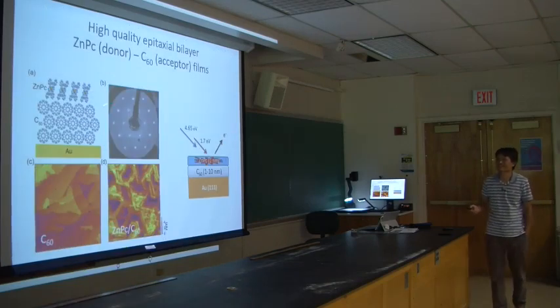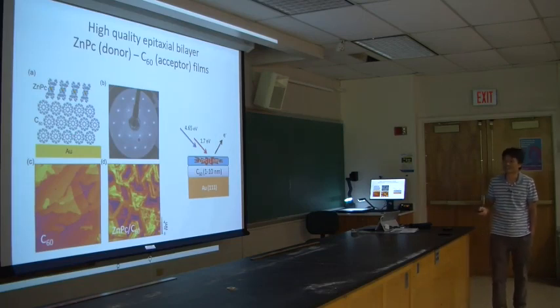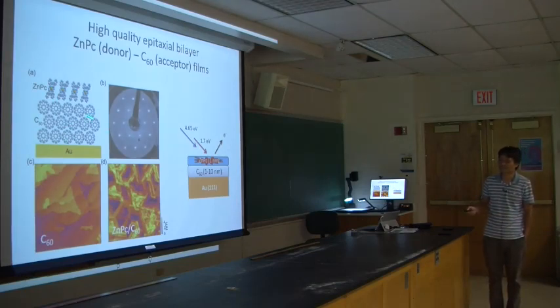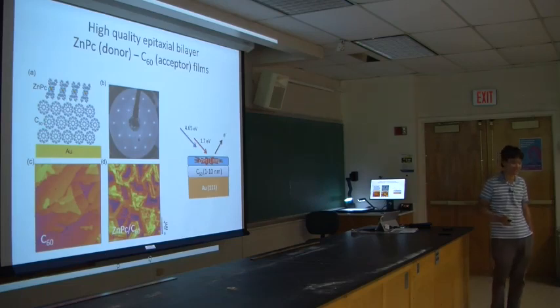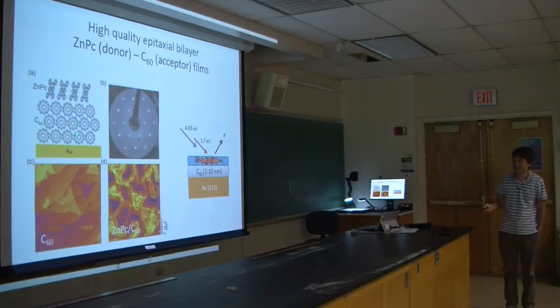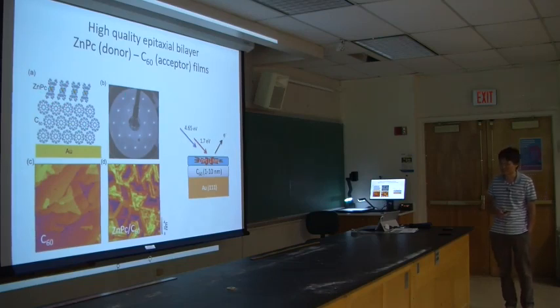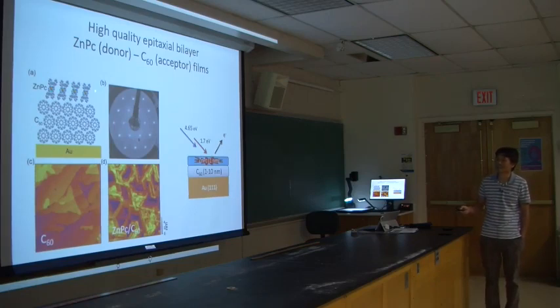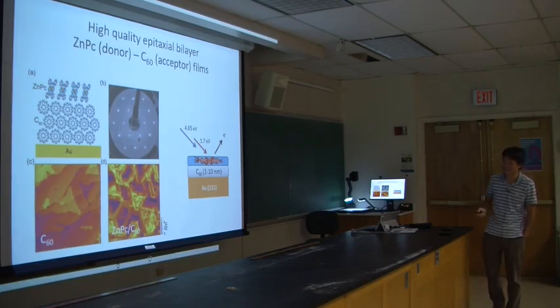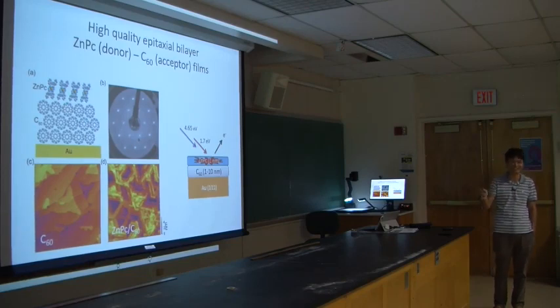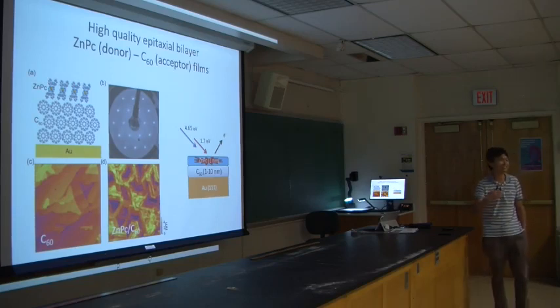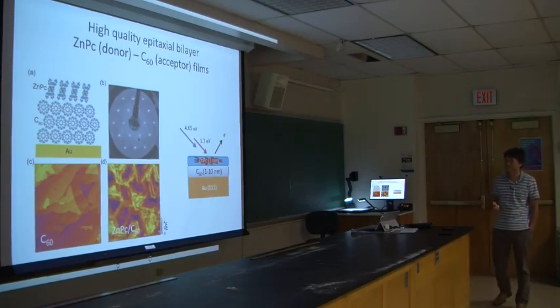So what we did is use a donor-acceptor interface, and we usually try to grow really well-controlled samples. In that particular experiment, we grew C60 molecules onto a single crystal gold surface. We have really nice epitaxial C60 on gold, and you can see that from the diffraction pattern here. Then we put the other molecules there. It turns out that in that case, these ZnPc molecules stand up and form a stack on top of the C60 molecules. We did some sample characterization, so we know the molecules are oriented the way that we draw it here. Then we can work on our experiment with this well-ordered interface.